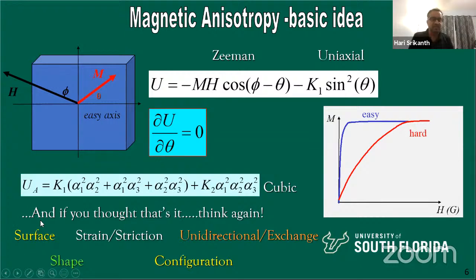We can actually play with the surface of nanoparticles and thus change the surface anisotropy and then change the shape of the hysteresis loop. The shape of the loop is key to our application, which is the heating efficiency for cancer therapy, okay? I'll get to that. So we, as physicists or material scientists, have to try to come up with ways to change or tune the shape of the hysteresis to improve the heating efficiency of these nanoparticles. So we can do that by various methods.